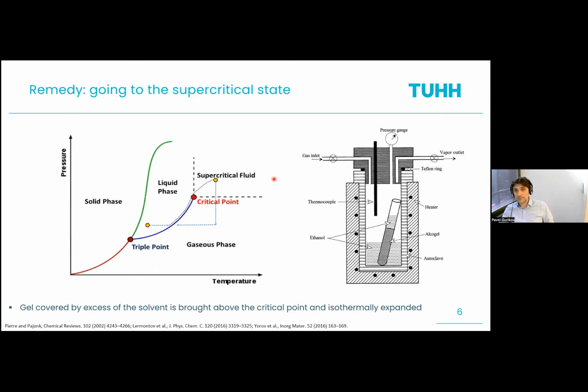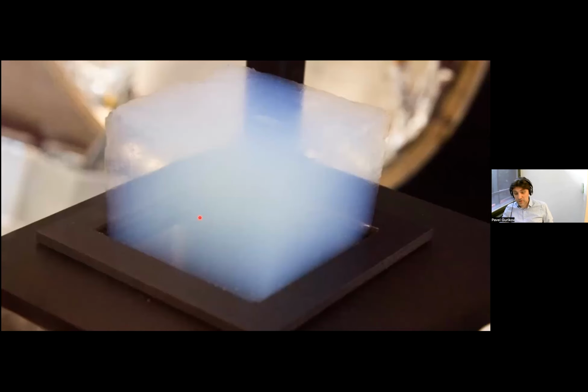And that's early, in the 30s of the last century, people did this and repeated it later on after an approximately 50-year delay. So they took a gel, brought it into a high pressure vessel, put an extra solvent on top, and then heated everything up just to be somewhere here during the process. And then they slowly let the solvent go out to avoid having a liquid phase in your material. And by doing so, they managed to produce what still fascinates me. Anytime I'm entering the lab, unfortunately I'm no longer so often in the lab, but as soon as I have the opportunity to touch, to feel, to smell any new type of material which is called aerogel, I always do so. And this is an example of silica material.